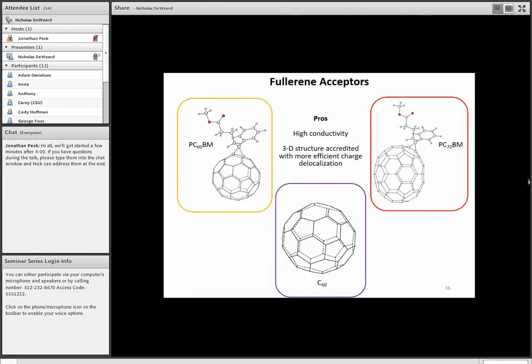So moving on to acceptors. Fullerene acceptors are by far the industry standard when we talk about acceptors in organic photovoltaics. They've been around since the beginning, and most of the highest efficiency devices are with fullerene acceptors, though that is changing now. But in pros, they have high conductivities, higher than the small molecule or polymer versions of acceptor molecules. They also have this 3D structure, referring to the buckyball. That 3D structure is believed to be responsible for more efficient charge delocalization, which allows charges to delocalize and become free carriers throughout the device much more efficiently than in their 2D acceptor counterparts, like small molecule acceptors.